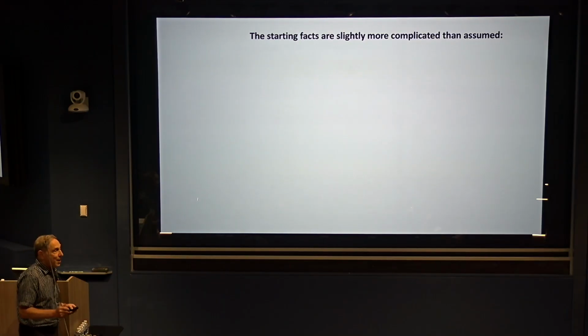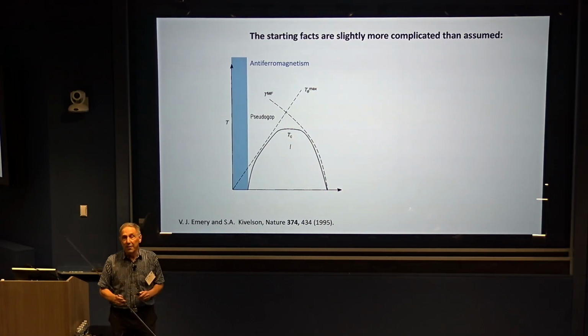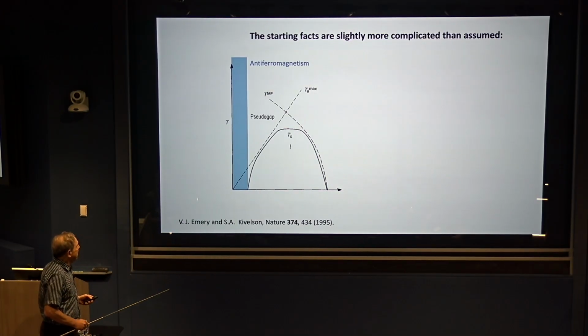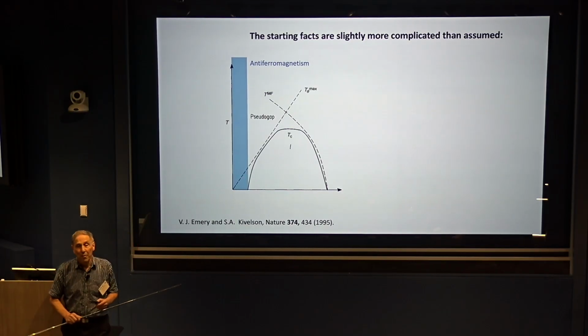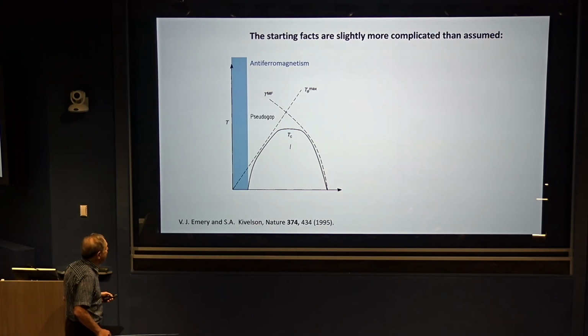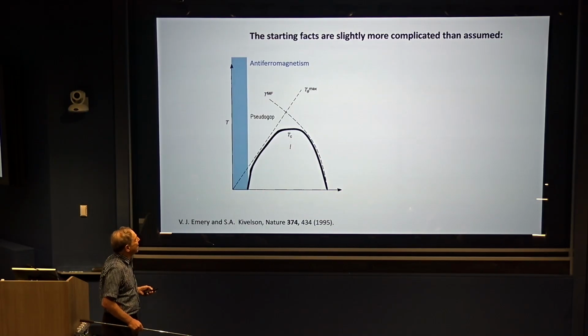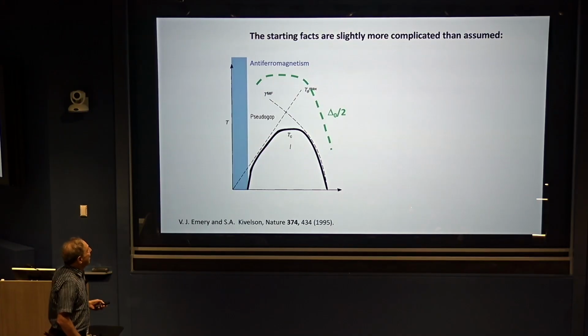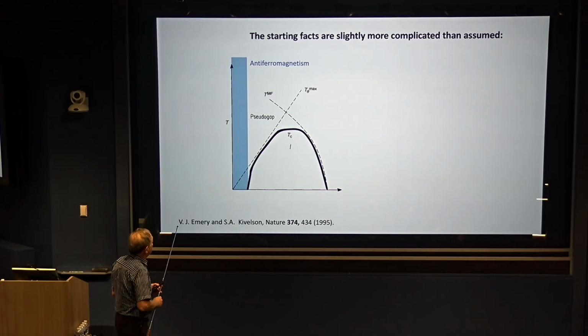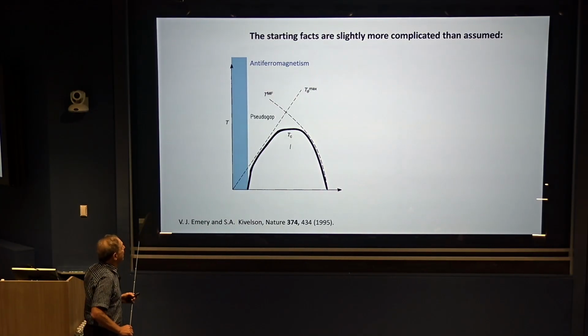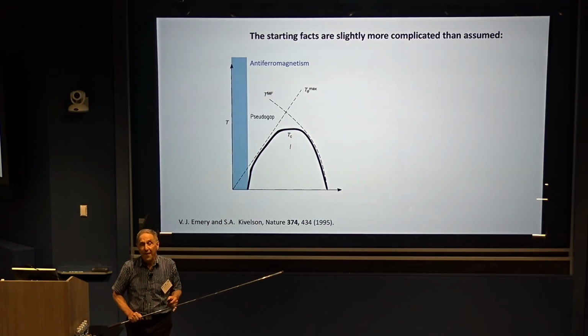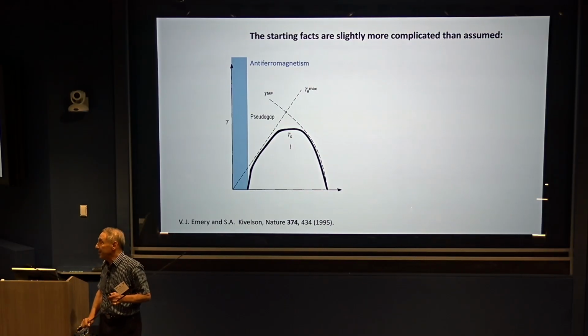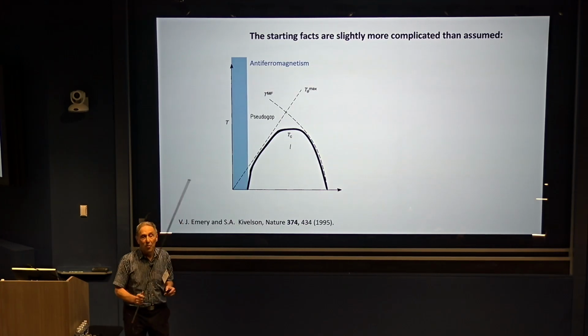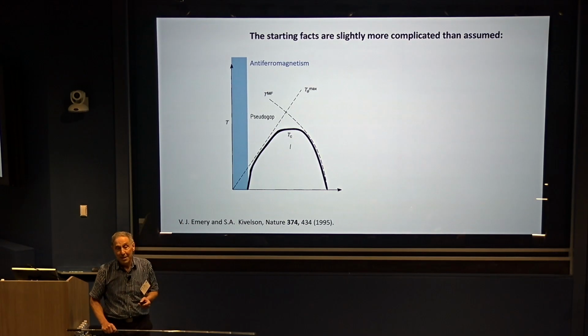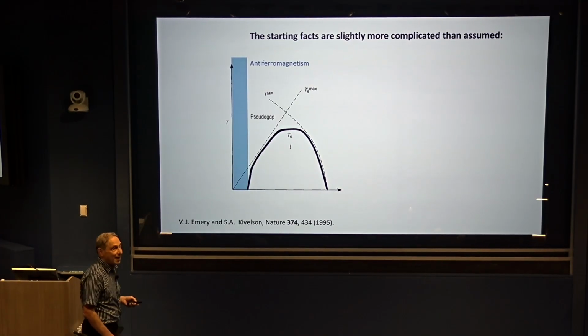Okay, so let me start with the properties that we think we know about the cuprates. There's a phase diagram of the cuprates with a superconducting dome. There was a perspective on this dome that Vic Emery and I put forward, and many other people had similar ideas: a crossover between a low doping regime, where TC is determined by phase ordering, with T theta the phase ordering temperature estimated from the zero temperature superfluid density, and an overdoped regime, much more BCS-like, where TC is determined within BCS mean field theory by the magnitude of the superconducting gap.